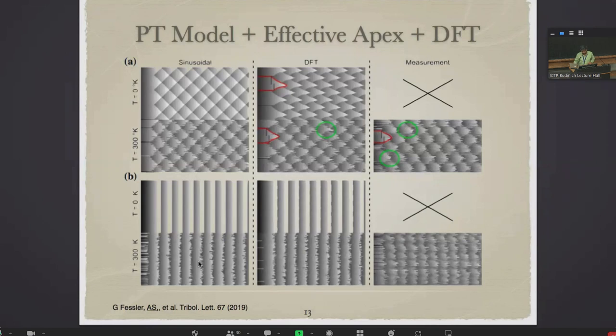Let me show you some results. Perhaps the most important results—let me go to the three questions that we are looking for the answers to them. First, the last question was: what is the origin of this tip trajectory asymmetry? From this asymmetric potential, which comes from the asymmetric tip apex, we saw these simulation results at the bottom. You can see that you can always find some trajectories, some scanning lines, on which the tip trajectory on forward and backward are not identical—I would say except the most trivial one, that is straight-straight in both directions. All four others can be reproduced by this kind of simulation. So far we assigned this asymmetry in tip trajectory to the asymmetry of tip apex.